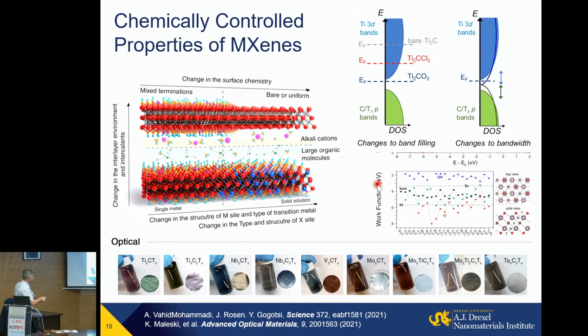You can have hydroxyl groups or oxygen. Surface terminations, hydroxyl, give you about 2 electron volt work function. Oxygen, 6 electron volt. Huge change, and you can tune it freely in between. And actually, you can change from oxygen to H by applying, for example, half a volt potential when you have a monolayer of water molecules in between, because you will protonate, deprotonate the surface. And this is very, very unique.